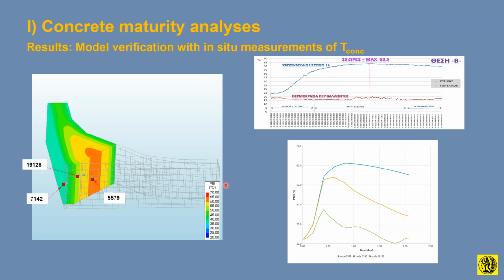First of all, we wanted to verify that we can match the physics which we measured. So we did a typical sub-assembly of the caisson in the footing area, and we measured the temperature generated in the center and in the perimeters given this heat generation model, and we found that in reality the temperature near the weather exposed conditions was matching fairly closely, 62 degrees, the measurement over a day and a half.